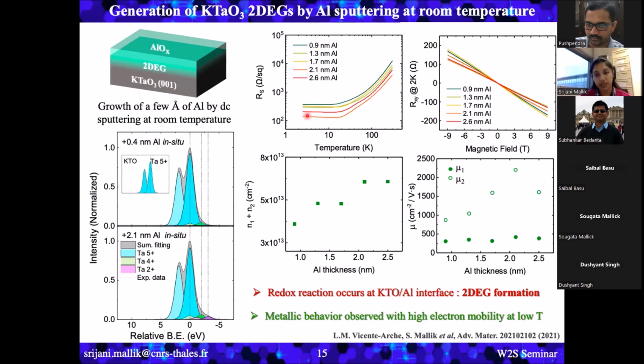And also we calculated the carrier density as well as the mobility of these samples from the Hall measurements. Here I would like to tell you that the mobility we achieved for the aluminium KTO 2DEGs is of similar order of magnitude to what we were achieving for the STO 2DEGs also. As I said, it's a comparatively newer system, so we really wanted to study the band structure of this 2DEG in very great detail.